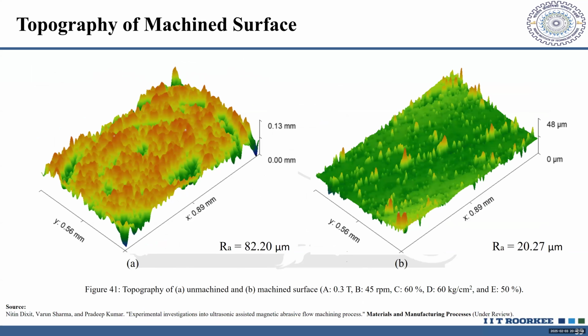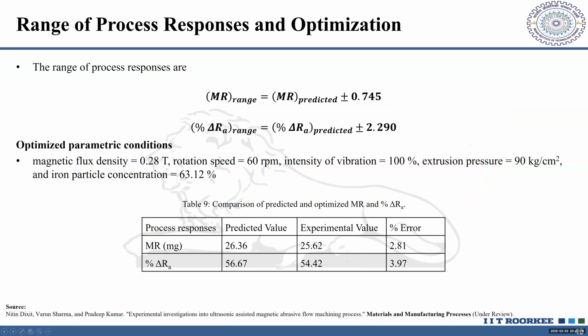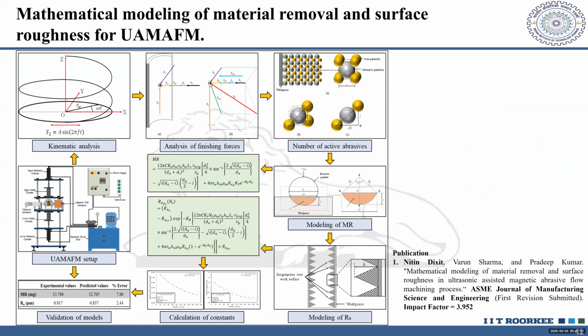You can see here that the initial unmachined surface has a surface roughness of 82 microns, whereas the desired surface finish for the machined specimen is of the order of 20 microns. We compared the statistical model, and it was very good. It had a percentage error of less than 5%, which is considered a conventionally good model for predicting the output responses in terms of material removal rate and percentage improvement in Ra. With that in mind, we try to understand the science behind this.